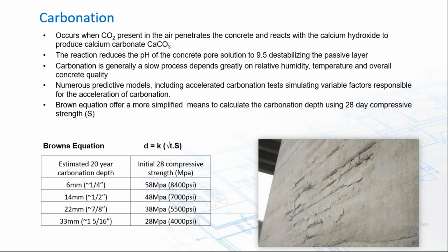There are plenty of predictive models out there, including accelerated carbonation tests simulating variable factors responsible for acceleration of carbonation. But the one that really puts it in fairly simple terms for me is this Brown's equation that says we take, let's say, 5,500 psi concrete, under normal conditions, a carbonation wave front will extend into concrete just under 1 inch, 7/8 of an inch, in a period of 20 years. Okay, so it is slow.